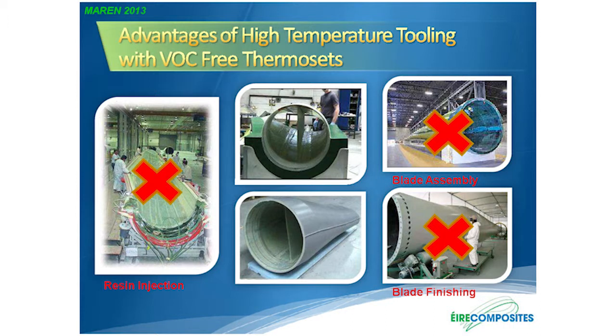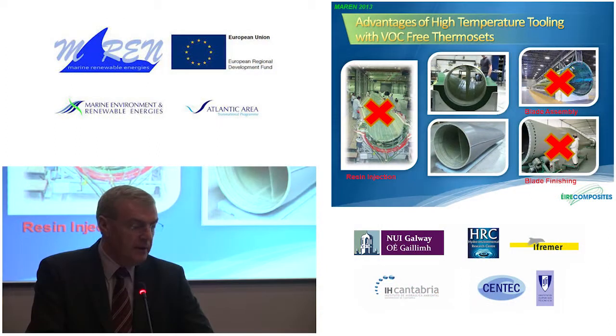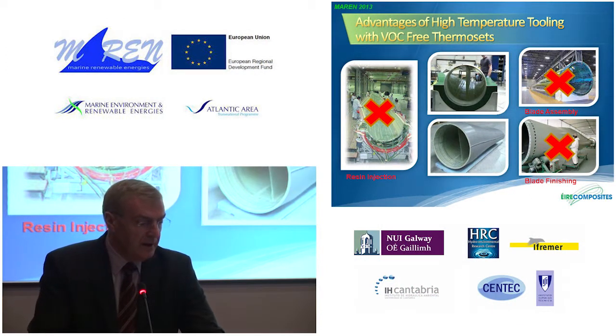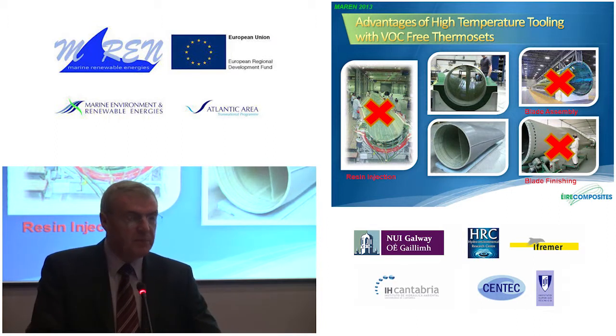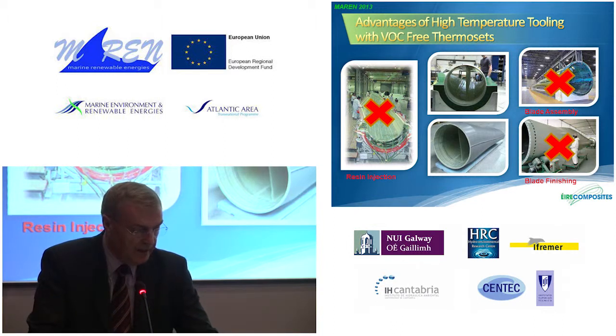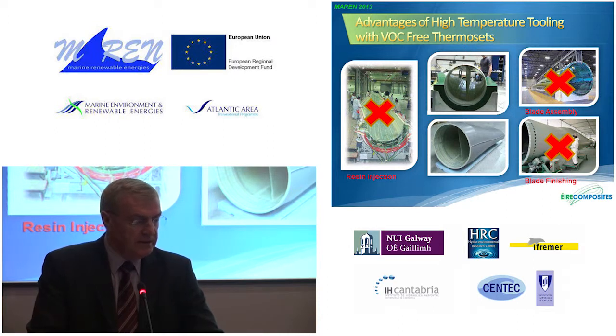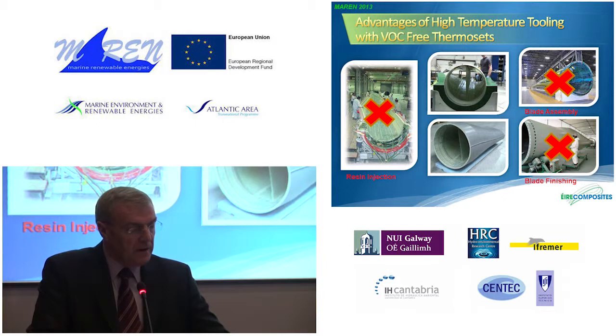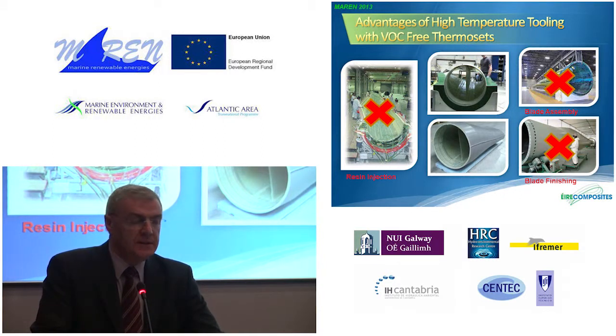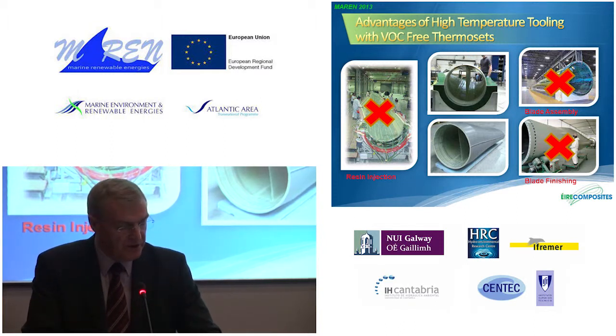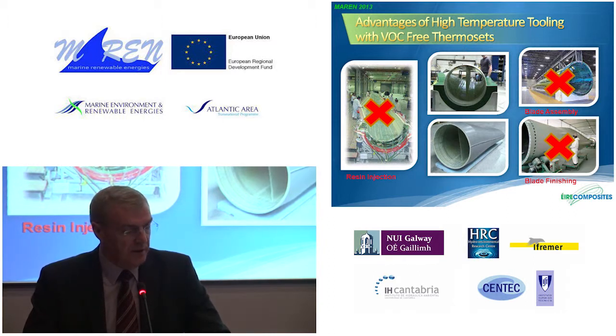So what that does for the process is quite interesting, in that if you see on the left-hand side here, where a standard system is used to produce a skin of a blade, it may not be as visible in the photograph as I'd like, but what you see is lots and lots of tubes and bags and extraction points along the length of the blade. And this is used to inject the resin into the fibre bed and extract any air out of it to allow it to wet out completely. Once that is complete, the entire bag and the tubing, etc., cannot be used again, because it's full of resin which has hardened at that point in time, and therefore there's a lot of waste in the overall production of a blade. Several 100 kilos of material are lost in the actual tubing, etc., that's used.